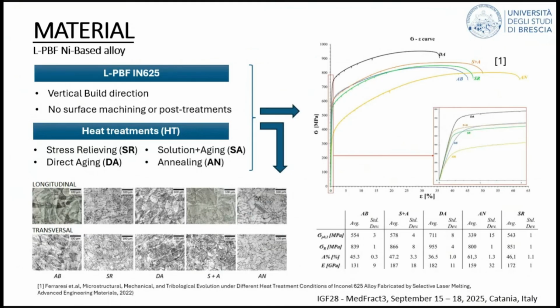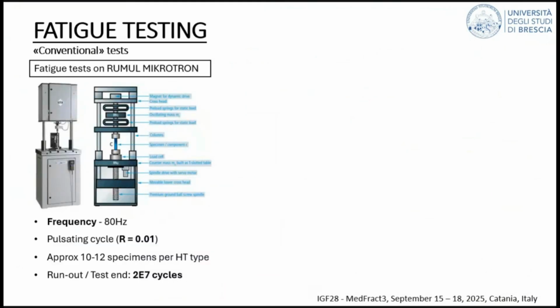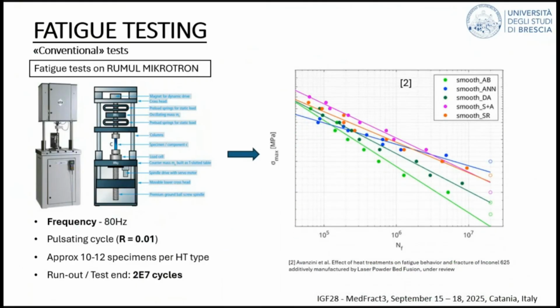The other information that we had as a starting point is that on the same family of materials, we carried out fatigue testing in a conventional way, with a pulsating cycle up to 20 million cycles. What you see here is a representation of the fatigue curves. I beg your pardon that I removed the stress level because this part of the work is currently under review. But what is important for today's presentation is that we have very different fatigue responses in terms of slope of the curve and in terms of fatigue strength for various cycle numbers.